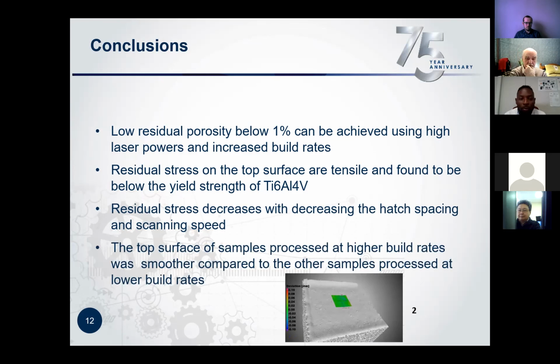And then another thing, when we look at the top surface, we can conclude that the top surface of the sample processed at high build rates was actually smoother compared to the other samples processed at the lower build rates. This really has to do with the increased overlap rate that we are applying. It influences the morphology of the layer and gives you this kind of smooth surface.